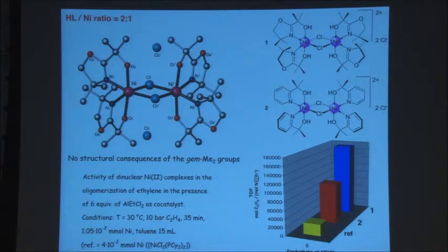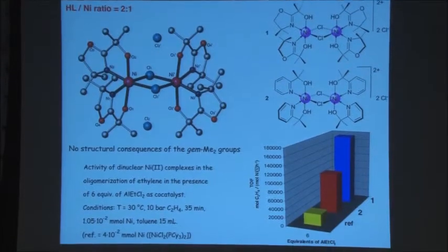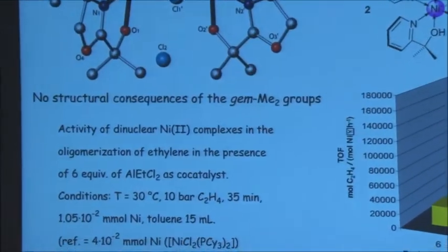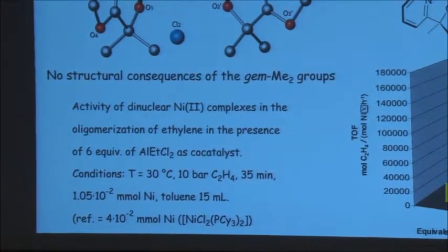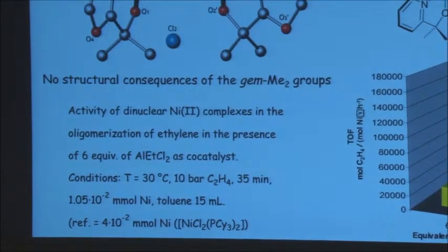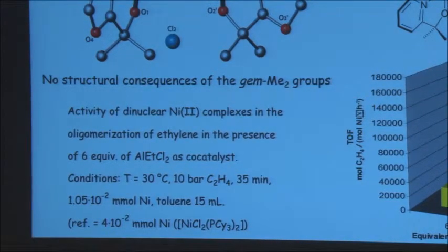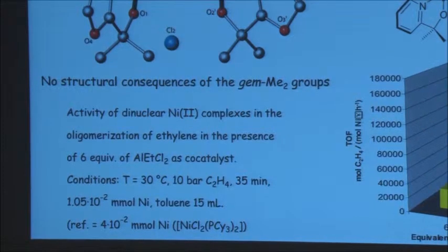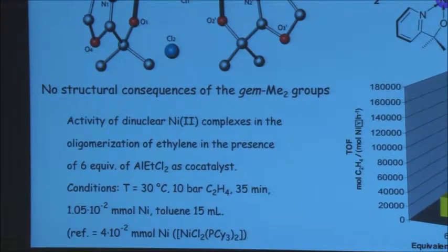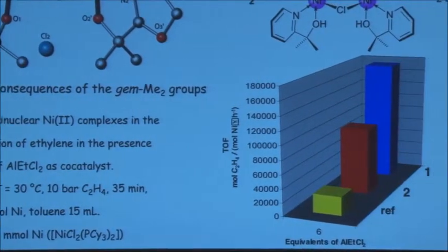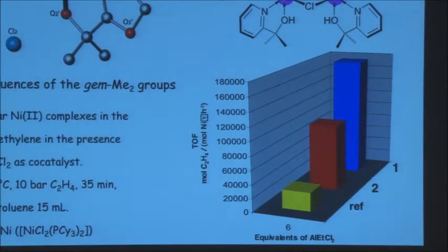If you look at the catalysis under similar conditions as before, we see again that compound 1, this time the oxazoline-based system, has a very high turnover frequency. So it's a very active system. Surprisingly, perhaps, but it's something that in catalysis you cannot always explain. Why is one system better than the other? You try to, but you can't always explain. This time, the oxazoline seems to be better than the pyridine, the red box here, which is still active, but not as active as the oxazoline one.